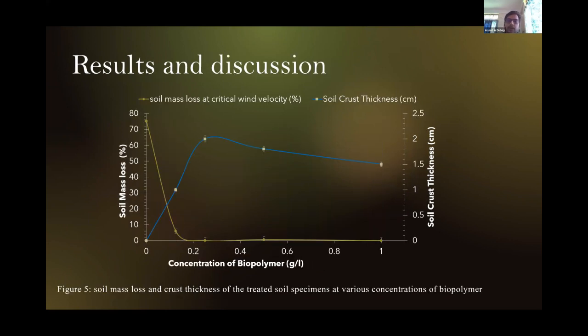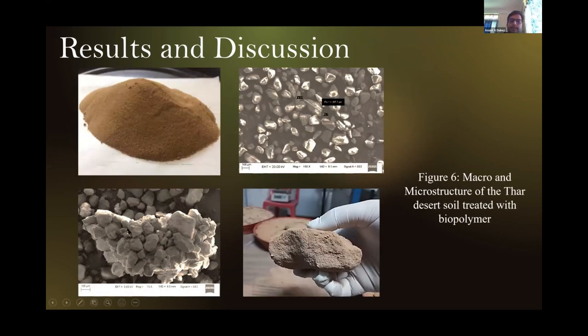These are the soil mass loss along with the crust thickness in the wind tunnel. These results are at 45 kilometers per hour velocity, and the exposure was for 15 to 30 minutes. As you can see, the green line shows the mass loss under the exposure of wind. At 0.125 gram per liter also, we found some detachment, some loss of mass, but it completely ceased at 0.25 gram per liter. These are the macroscopic and microscopic images. This is the pure sand, which is loose and smooth in nature. Once the biopolymer is applied, the particles are combined and joined together by the action of the biopolymer, and a thick crust is observed.